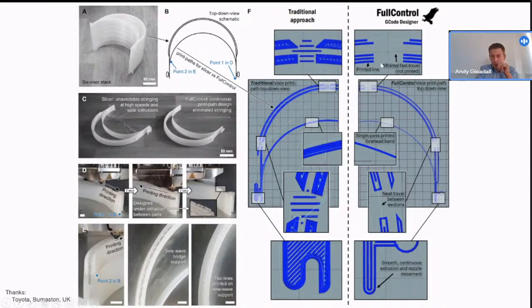But then with full control, we knew what the limitations of the material were in the printer. We knew there were going to be defects. We couldn't just instantly stop printing and start printing somewhere else. It was going to leave a string because we were printing so fast, but we were able to control exactly where all those defects happened. So there were these holes in the mask that you can see on the front and sides, and they were a really easy place to put the defects, because then we could come with a drill and just drill through them, get rid of the defects, and it took 10 seconds to post-process the mask instead of 10 minutes.